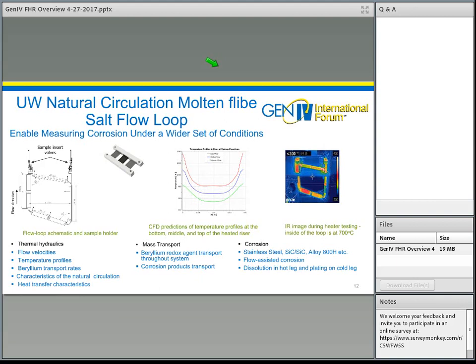Likewise, the work at UW has moved to the point of going beyond static corrosion testing to looking at natural circulation loops. And these have been constructed, and actually within the next couple of weeks we expect the first natural circulation loop at Wisconsin to be filled and to begin testing under more prototypical conditions with flow and temperature differences, and being used then to study for corrosion. These types of loops were used extensively back during the original molten salt reactor program, which ran at Oak Ridge National Lab back in the late 50s through early 1970s.